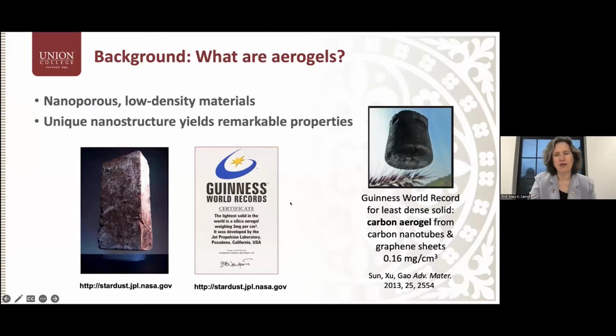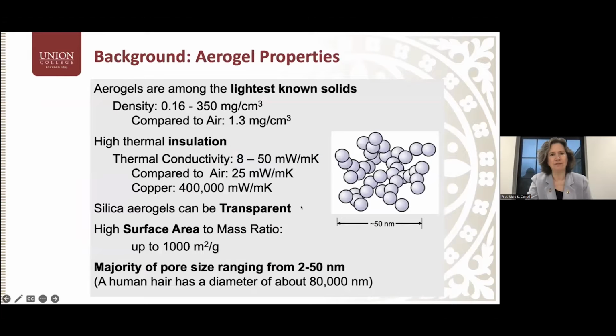At the time, there was a record for silica aerogels made by the NASA Jet Propulsion Laboratory in California for the Guinness World Record, but that record did not stand for very long. Actually, carbon aerogels, and in particular, aerogels made from carbon nanotubes and graphene sheets, as far as I know, currently hold the Guinness World Record with a density of 0.16 milligrams per cubic centimeter. So the materials have a solid matrix with a lot of pores, and the pores are filled with air, hence the name aerogel. Now, as I just mentioned, they are among the lightest known solids.